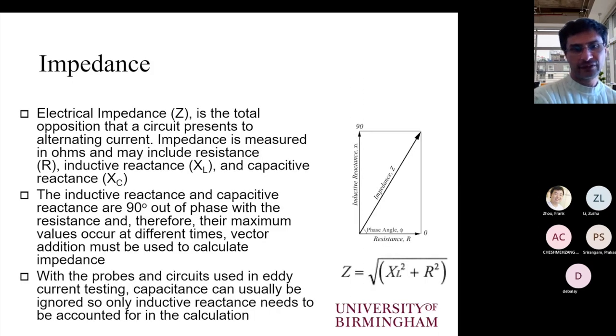In the classic approach, eddy current testing is looking at the impedance plane. So we see how the impedance of the coil changes. And since the impedance has three characteristic inputs, we need to take into account resistance, inductive reactance, and capacitive reactance. However, because we are dealing with a coil, we can consider that the capacitive reactance has a negligible value or is equal to zero. So we can exclude that, and that leaves us with the resistance of the coil and the inductive reactance, or the resistance of the circuit, if you prefer, and the inductive reactance of the circuit.